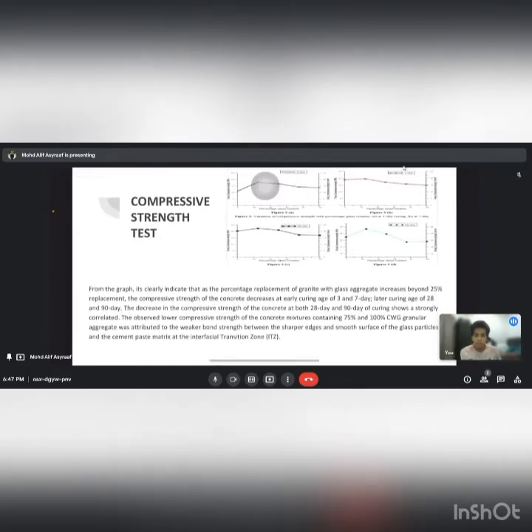Next is the compressive strength. From the graph above, it clearly indicates that as the percentage replacement of granite with glass aggregate increases beyond 25% replacement, the compressive strength of the concrete decreases at the early curing ages of 3 and 7 days.